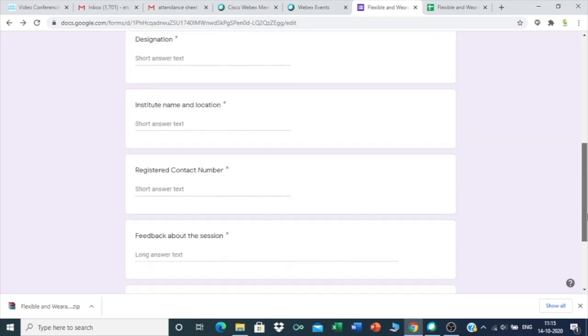When we disperse that and try to coat, this isopropyl alcohol will be easily evaporated. But if it's not, when you are spraying, because it is a liquid, sometimes more liquid will come to one side, less liquid to the other side. This kind of problem may occur while coating. So in such cases, your nanoparticles are deposited more at one side, less at the other side. This is the problem. But if you are taking a preheated polymer, this heat will help in evaporating your isopropyl alcohol much faster, so that you can get a uniform coating of your conducting part. That is one precaution you can take.